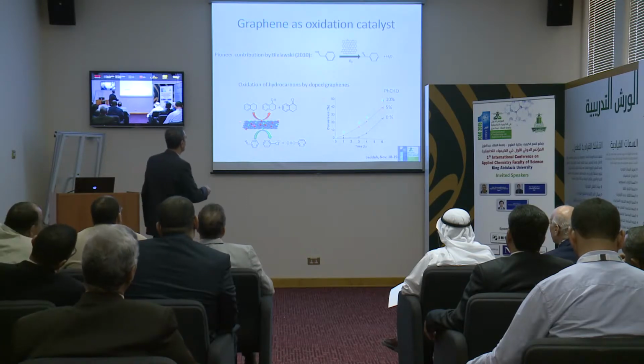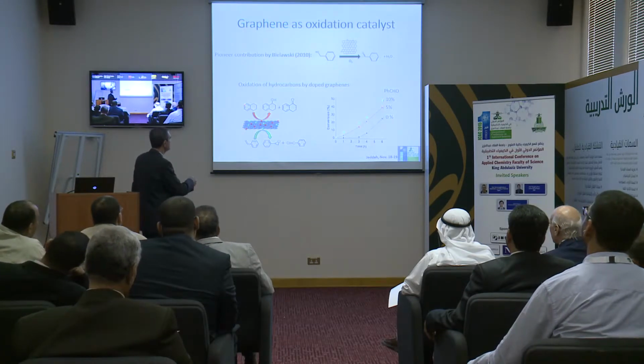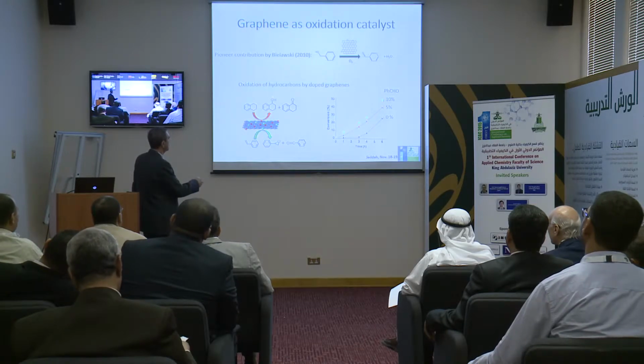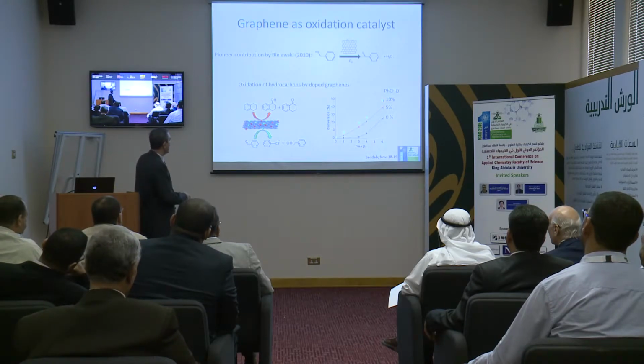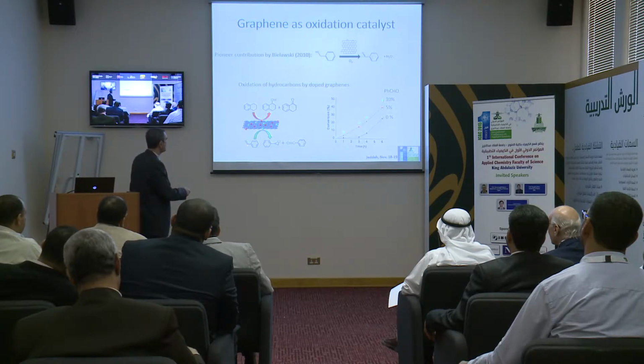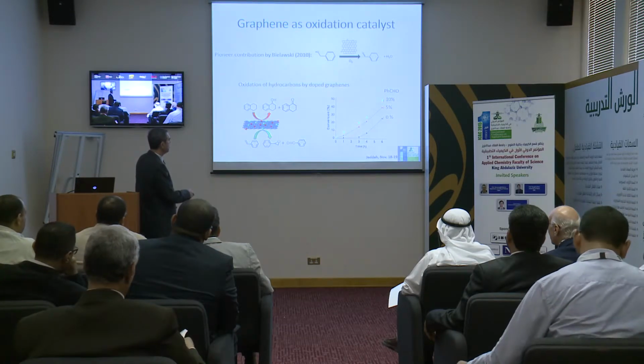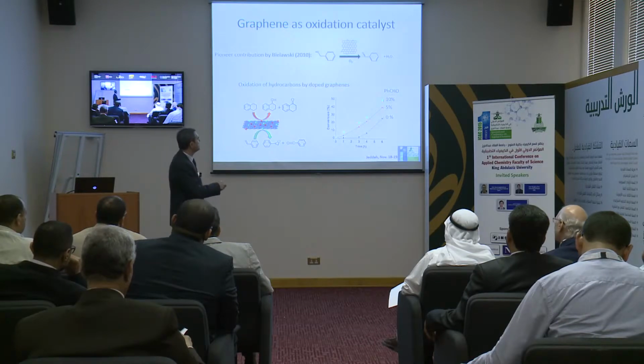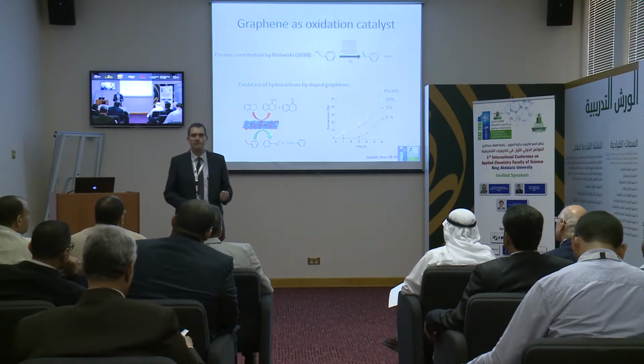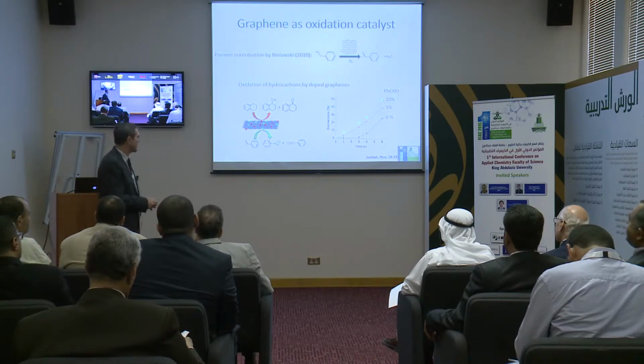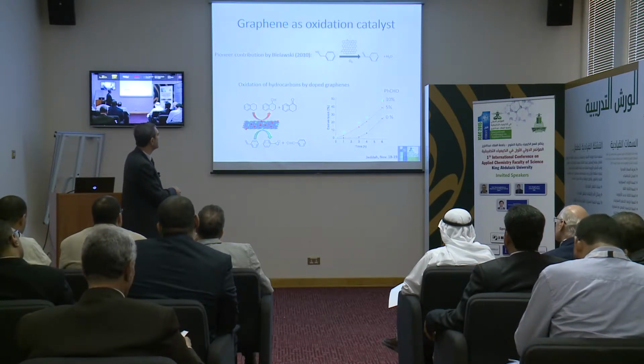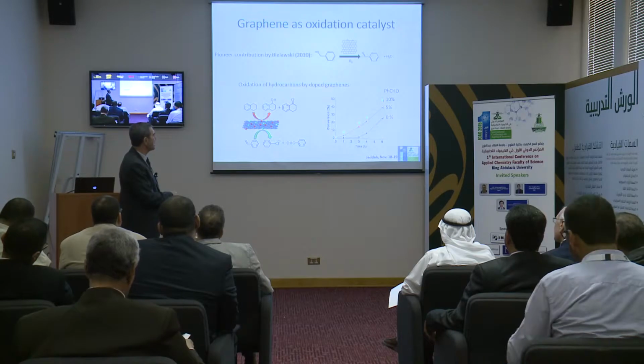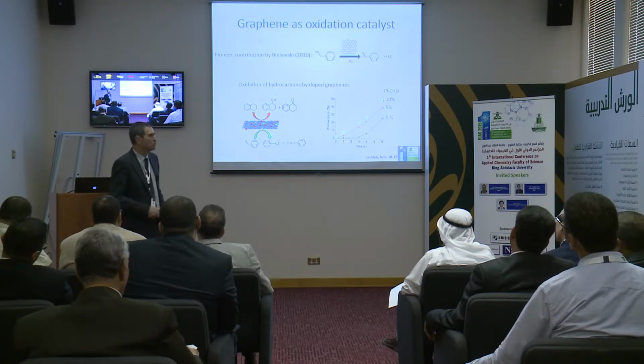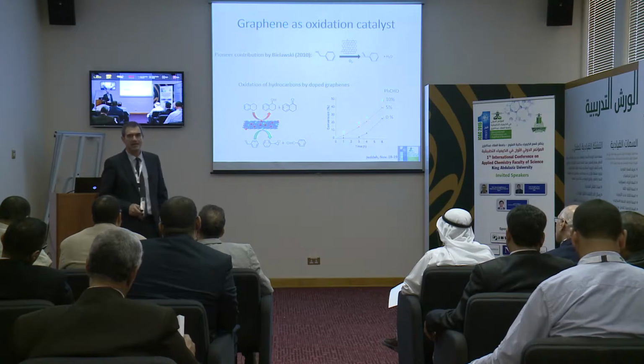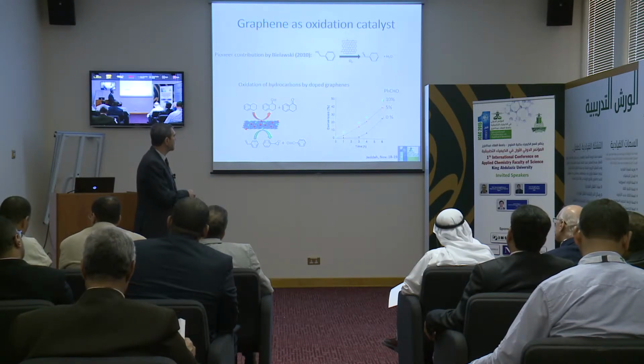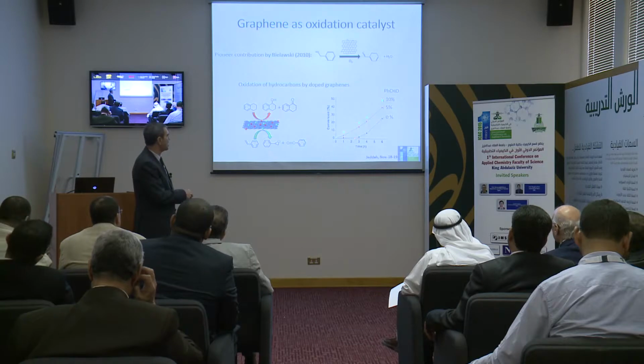And in that way, we can oxidize benzylic positions. For instance, in this case, we obtain the alcohol and the ketone just using oxygen. And also, we are able to oxidize carbon-carbon double bonds of alkenes to form epoxides and aldehydes. And this is very interesting because when you follow the kinetics of the reaction, you observe that using this carbon catalyst, there is always an induction period. An induction period because the mechanism of this reaction is always a radical mechanism. So we need some time to generate some radicals, in this case about 3 hours.